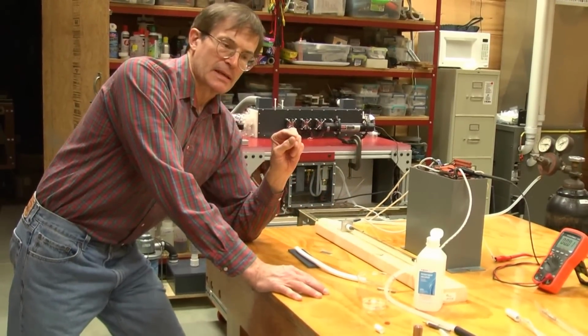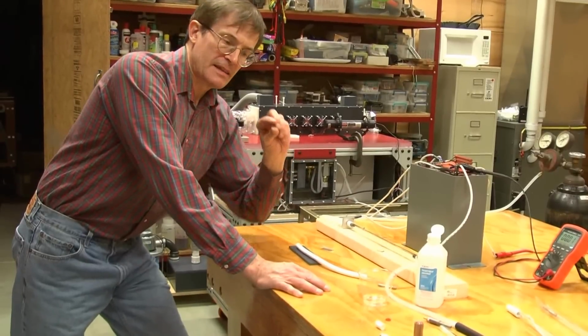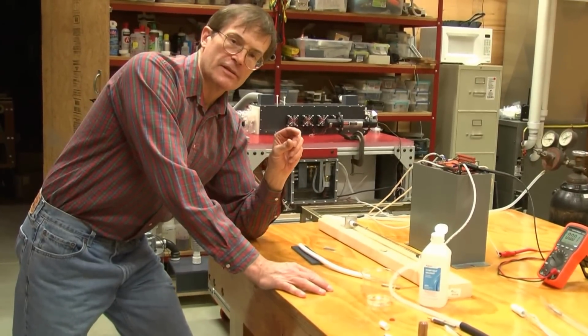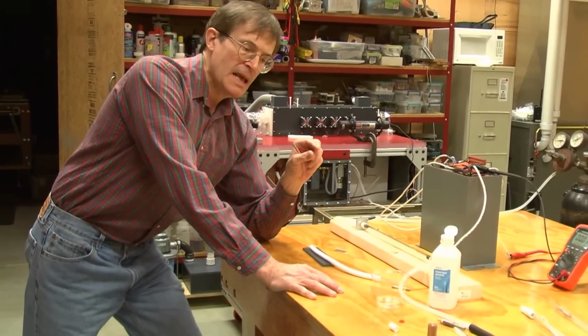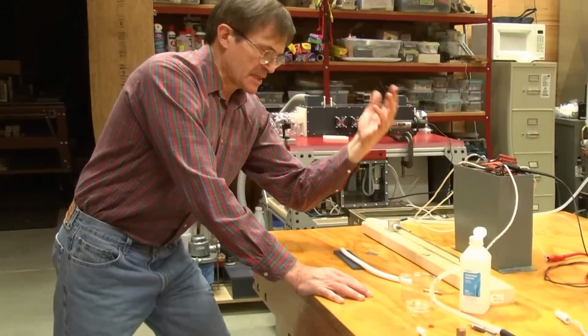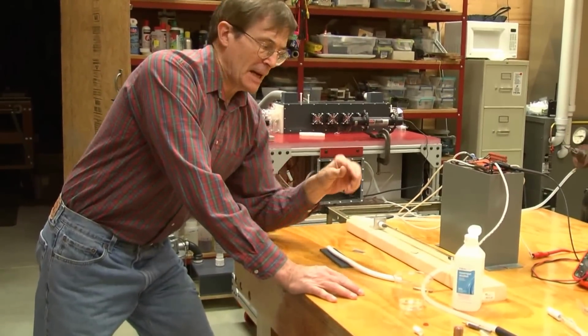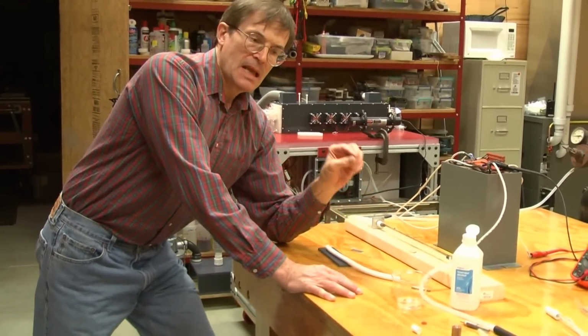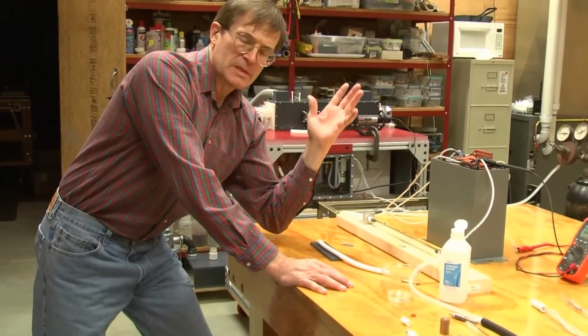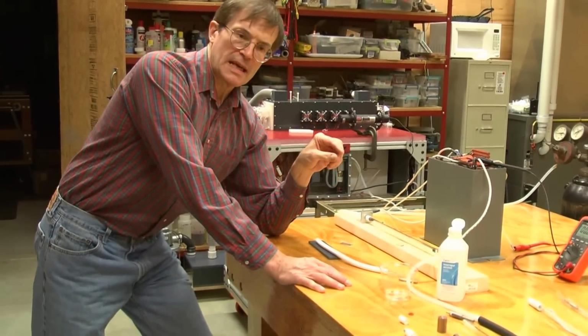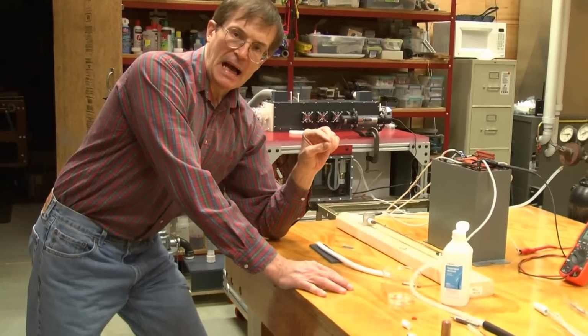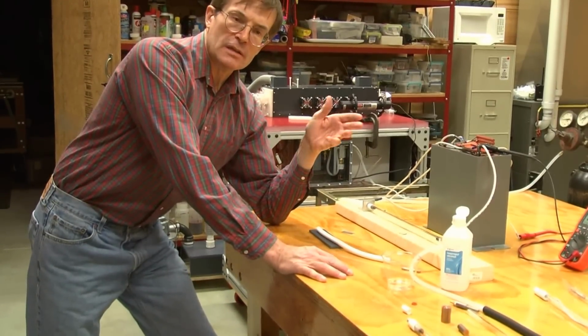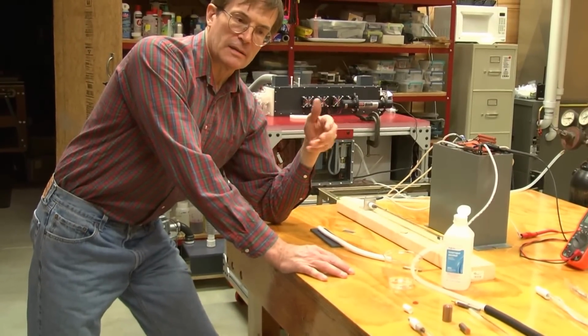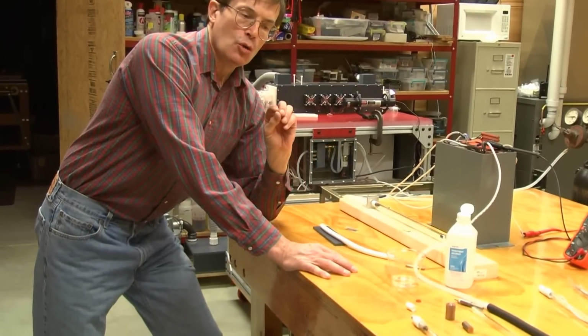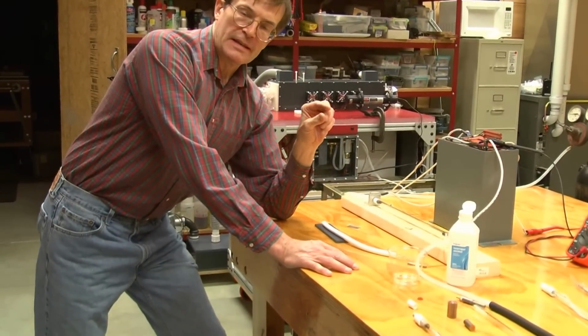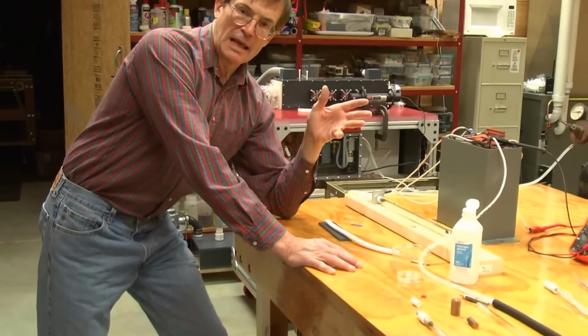What I think is happening is the silica and the oxygen are forming a thin annular shell right underneath their source, which is the quartz wall. And the low pressure gas, whatever it is, nitrogen, helium, remains the dominant conductor throughout the system. And it is this gas, which is at enormous temperatures, maybe 30, 40,000 degrees K, that's producing the high velocity ions and the very extreme ultraviolet photons, which are then absorbed by that outer layer and which is re-emitting them as a black body.